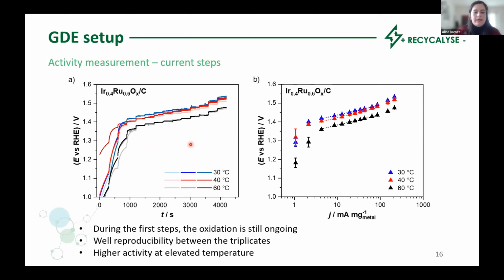On the A graph, we can see the response of those current steps for the iridium-ruthenium catalyst. We can see that during the first step, we cannot reach a steady state behavior. And this is due to an ongoing oxidation of the catalyst. So during this step, we are going from metallic catalyst to an oxide catalyst. After these steps, the catalyst reaches a steady state behavior.